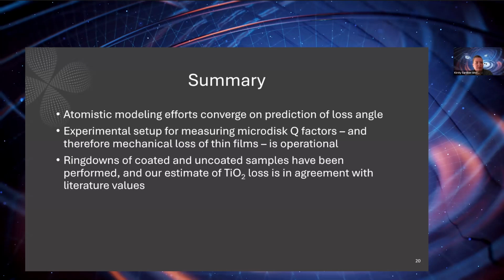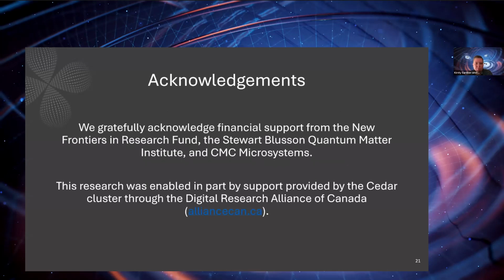So in summary, the atomistic modeling efforts converge on a prediction of loss angle. Our experimental setup for measuring microdisc quality factors and therefore the loss of thin films is operational. And our recent ringdown measurements of coated and uncoated samples produce an estimate of titanium dioxide loss that's in agreement with literature values. So this all works.